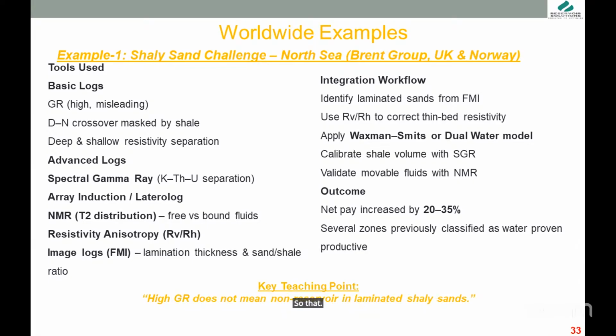This is the benefit of not using just Archie. Archie here is a miss. How to solve this issue? The basic logs here are gamma ray and density neutron crossplot masked by shale, so that the porosity reading is not good, with deep and shallow resistivity separation. Advanced logs we used here: spectral gamma ray, array induction laterolog, NMR, T2 distribution, free versus bound fluid, resistivity anisotropy, and the image log.